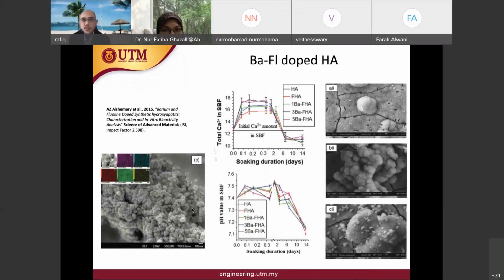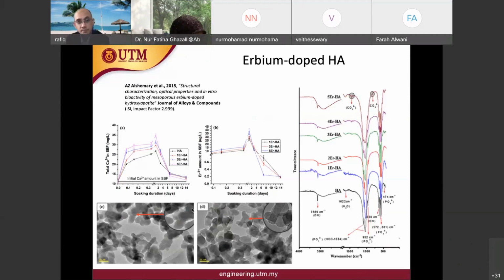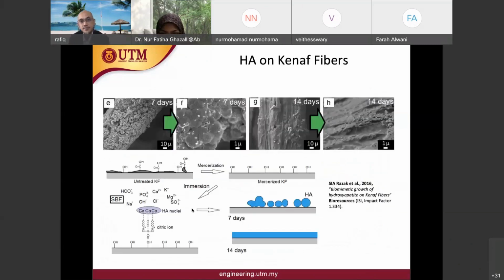Barium fluoride doped hydroxyapatite, another work on hydroxyapatite, doping of hydroxyapatite with barium and fluorine. And we look at the in vitro bioactivity of this barium fluoride doped hydroxyapatite. We have another doping of hydroxyapatite with erbium. Yeah. And this one we published in Journal of Alloys and Compounds. And so, successful development of erbium doped hydroxyapatite.